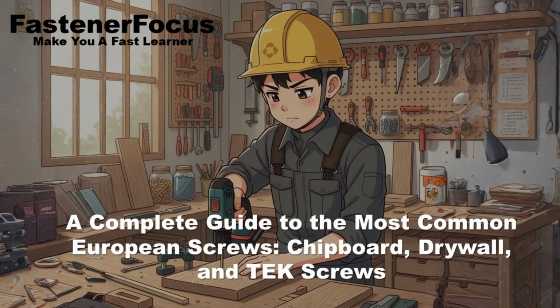That sounds dangerous. What is hydrogen embrittlement and why does electroplating cause it? Hydrogen embrittlement is a silent killer in high-strength fasteners. During the electroplating process, trace amounts of hydrogen atoms are absorbed into the crystal structure of the steel. Because high-strength steels are inherently harder and have a less ductile structure, these hydrogen atoms interfere with the internal bonding, leading to a dramatic loss of ductility. Exactly. The fastener can be installed successfully, but under subsequent stress, sometimes days or weeks later, it cracks catastrophically without warning.